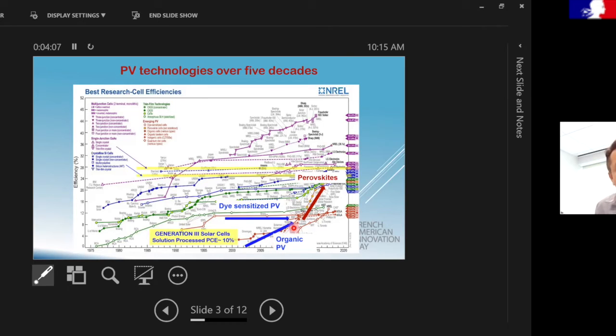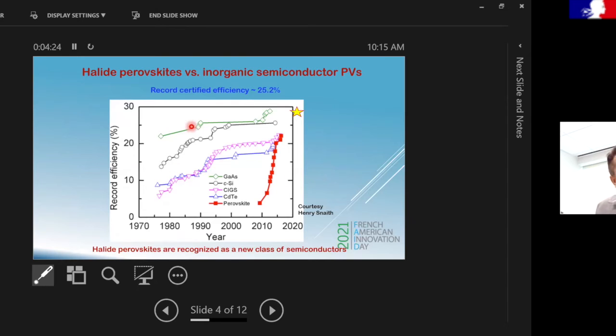And then in about 2009 and 2010, there was a disruptive breakthrough, which came in the form of these perovskite materials, where people were able to go from about 3% to now about 25%. And to put things in perspective, if you compare the perovskite efficiencies to other semiconductor materials, you'll see that this has had an exponential rise. This is really unprecedented for any material system; this has never really been observed.